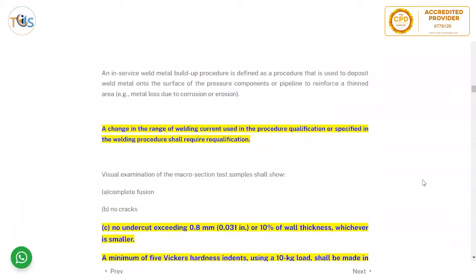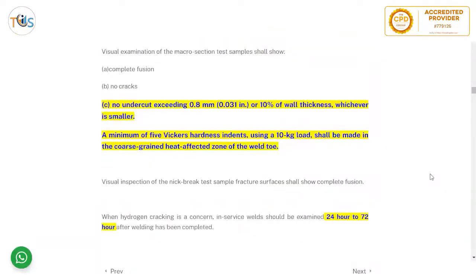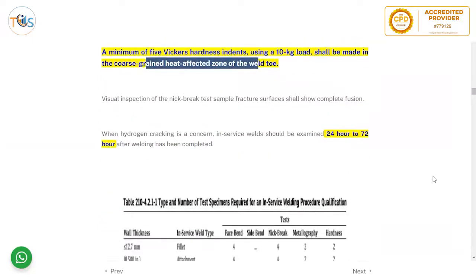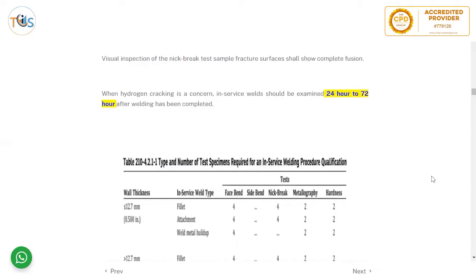Visual examination of macro section test samples shall show complete fusion, no cracks, no undercut more than 0.8 millimeter or 10% of wall thickness, and a minimum of 5 Vickers hardness indents. So this could be how many hardness tests you should do. Using a 10 kg load shall be made in the coarse grained heat affected zone in the HAZ region of the weld toe. Visual inspection of nick break test sample fracture surfaces shall show complete fusion. And hydrogen cracking is a concern, and in-service weld should be examined 24 to 72 hours after welding has been completed. This is due to delayed cracking of hydrogen.